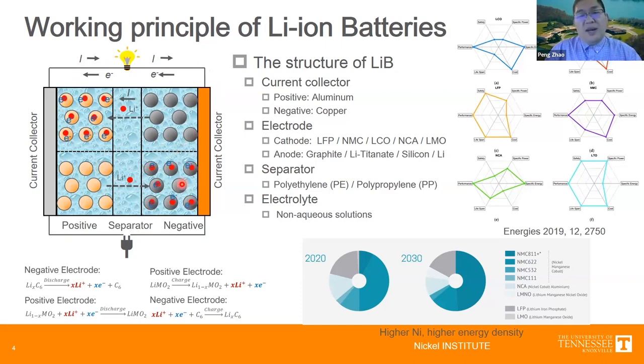And depending on the different chemistry, there can be different cathode materials like lithium iron phosphate, nickel manganese cobalt materials, lithium cobalt oxide, nickel cobalt aluminum, and lithium manganese oxide. There can be different anode materials as well. So these different batteries may have different performance, as I summarize here. And recently there is a trend that the NMC cells are gradually evolving to those with higher nickel content, which leads to higher energy density.